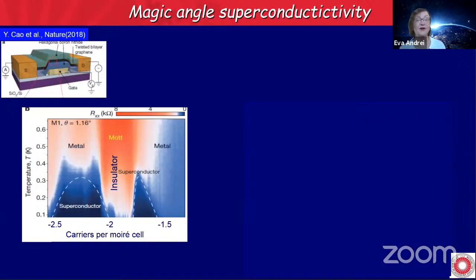And so this is what people started doing, and this is the group of, in the MIT group of Pablo Jarillo-Herrero. They made a field effect transistor out of graphene. So you have a twisted bilayer graphene here that is protected from top and bottom by boron nitride. It's protected from random potentials that would come from various substrates, and then they cooled it down close to absolute zero.